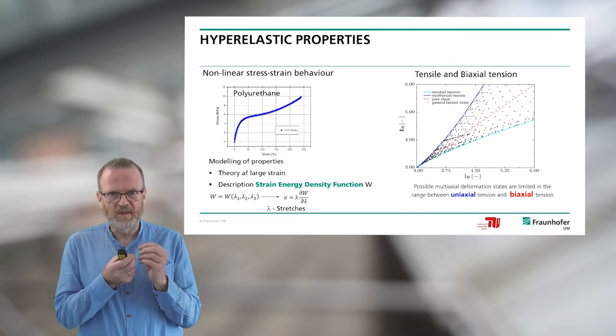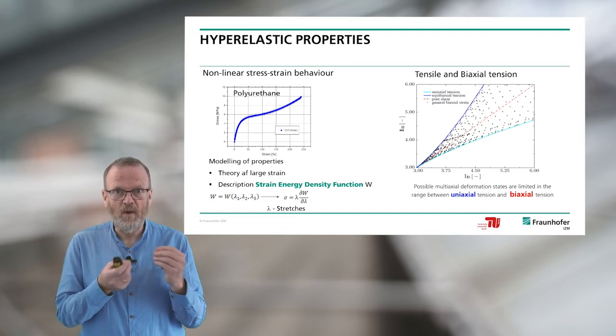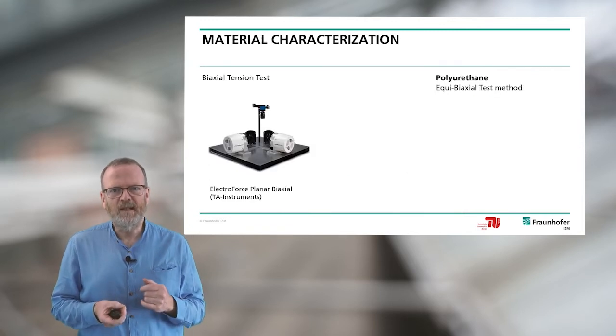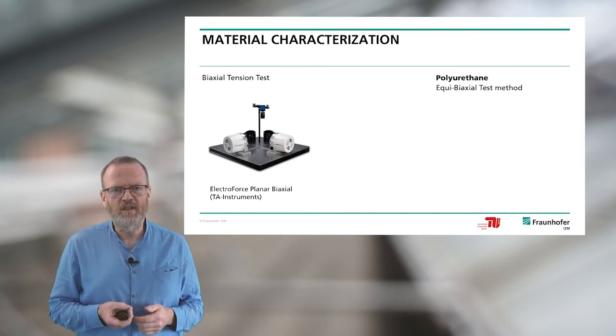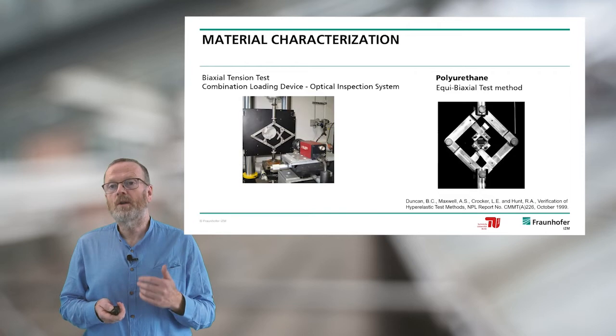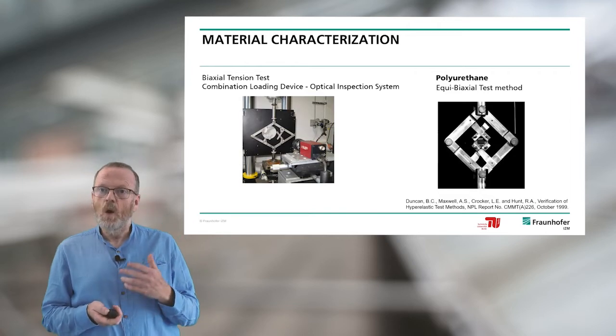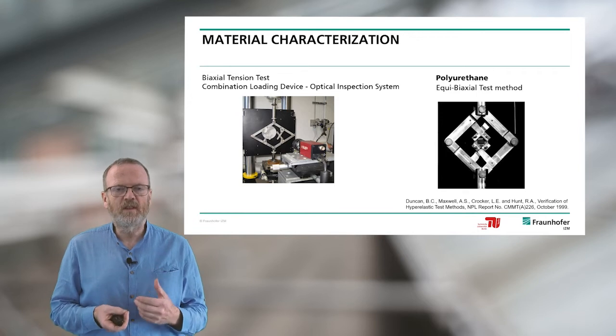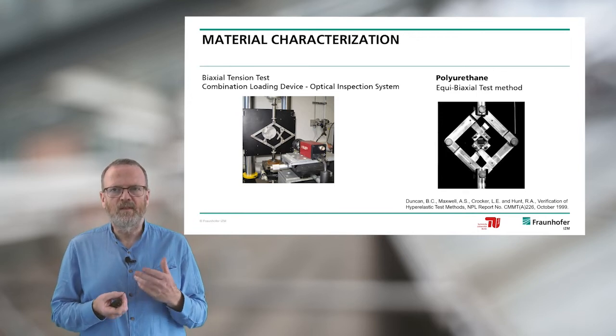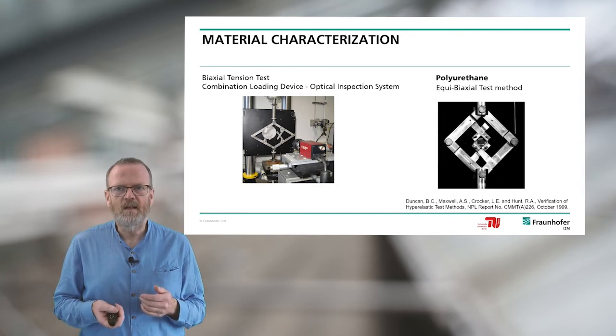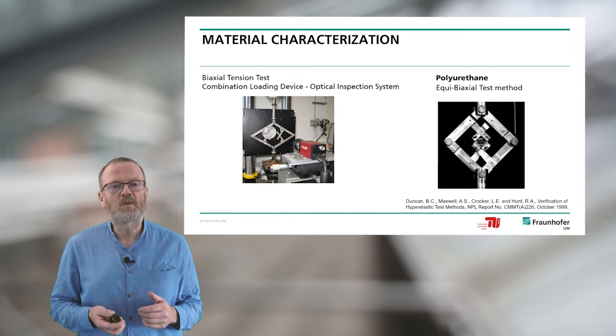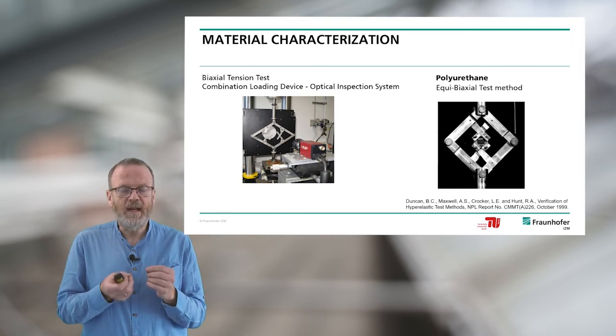Altogether, we can describe the material properties for the hyper-elastic materials — the non-linear stress-strain behavior — over a wide range including the multi-axial deformation field. To determine these biaxial material properties, you can use a conventional biaxial tension tester, or you can develop your own measurement system. We have developed in our lab the equibiaxial test method, using conventional test equipment with a developed scissor-like test system.